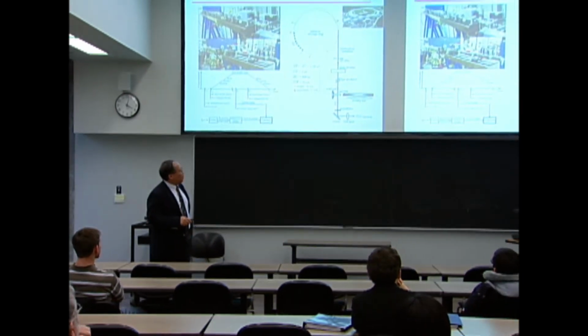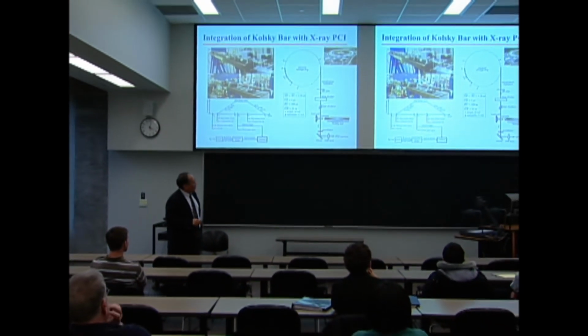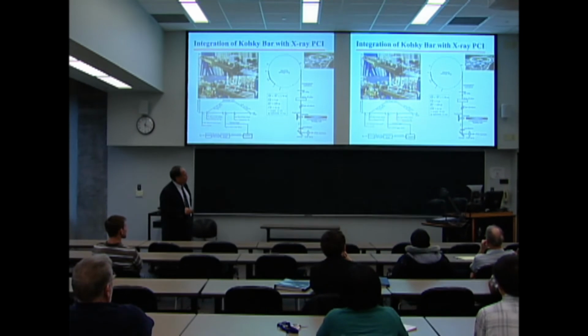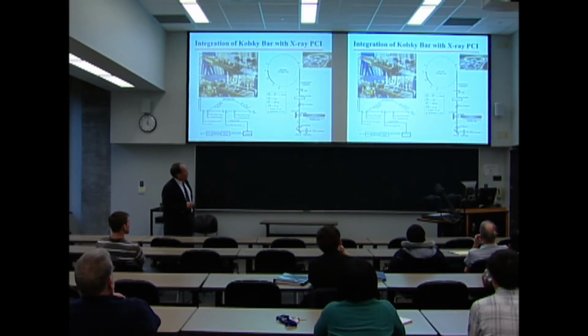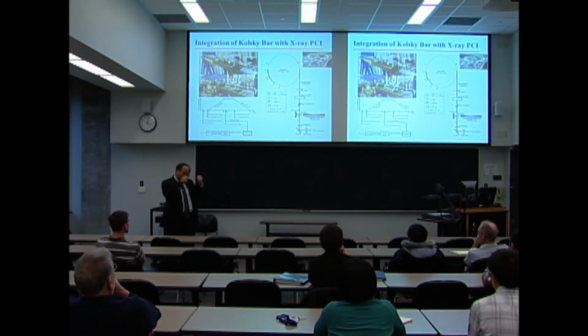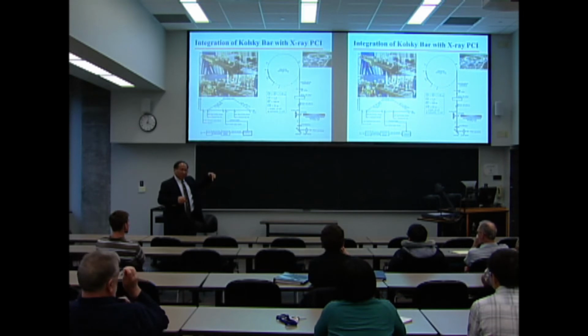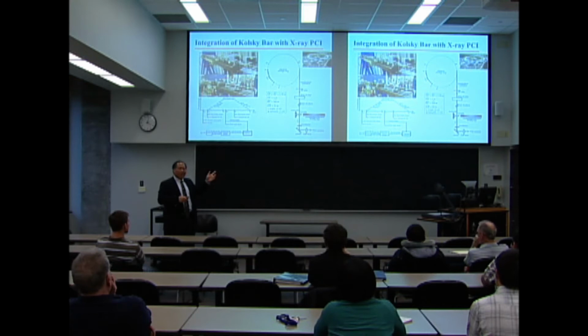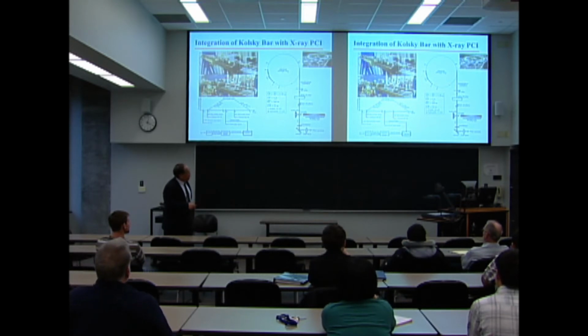Then you need some smart people because there's a lot of coordination you need to do. This is my loading bar. This is a sample. There's a load cell behind it. So you need to make sure that X-ray comes while sample is being stress wave loaded. X-ray is so strong, you cannot allow it to come early, otherwise it will burn up your sample. And you have to shut it off right after loading. Otherwise, it burns everything along its path. So you need to have the coordination with all the shutters.